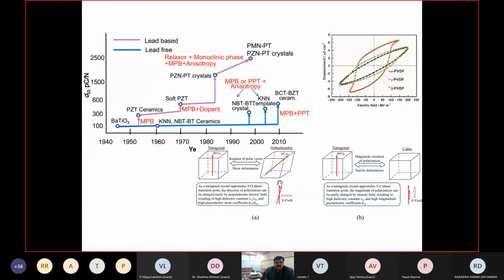So I can tell you some names here that you can see. First one is barium titanate, second one is PZT, that is lead zirconate titanate, then soft PZT, PZN-PT crystals, PMN-PT crystals, then KNN sodium potassium niobate, NBT-BT sodium bismuth titanate, and barium titanate. So there are a lot of materials on which people are working, but still the maximum value of D33 up to 2010 that is reported in lead free materials is 600, but in the case of lead based single crystals it is nearly 2500. So there is a huge difference. So that's why a lot of people are working to get a higher value of D33 by doping, by modifying the synthesis process. So work is going on.